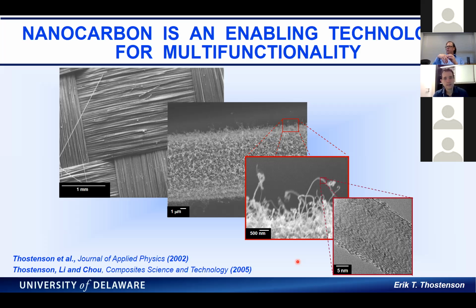These were bonded to the surface, but they weren't super strongly bonded. More recently, we've done the microdroplet test on electrophoretically deposited material, and it is chemically bonded to the surface of the fiber. We validated that with a lot of XPS and a model interface system. It's that chemical bonding at the fiber which really makes it so nice for the smart garment, because those are extremely well bonded to the surface of the fiber.